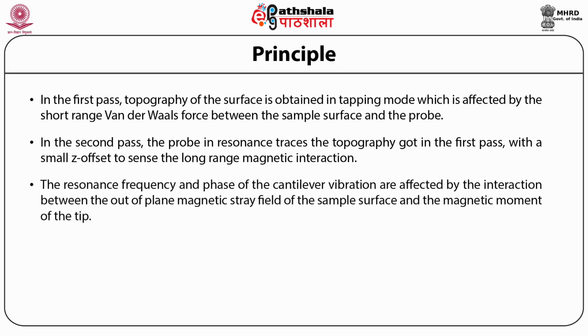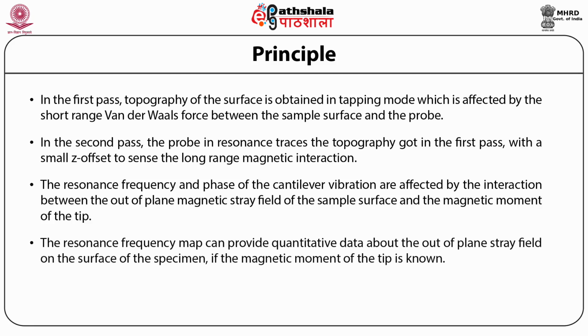The resonance frequency and phase of the cantilever vibration are affected by the interaction between the out-of-plane magnetic stray field of the sample surface and the magnetic moment of the tip. This interaction is effective in the range of 10 to 100 nanometers. The resonance frequency map can provide quantitative data about the out-of-plane stray field on the surface of the specimen if the magnetic moment of the tip is known.